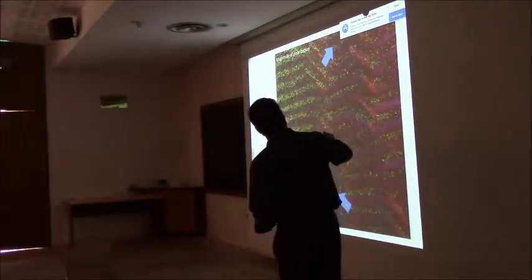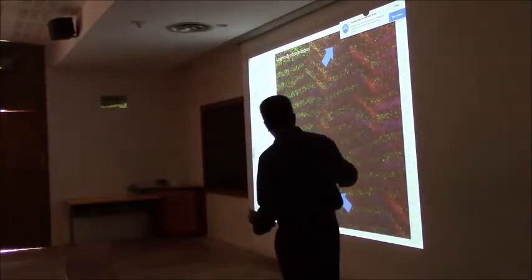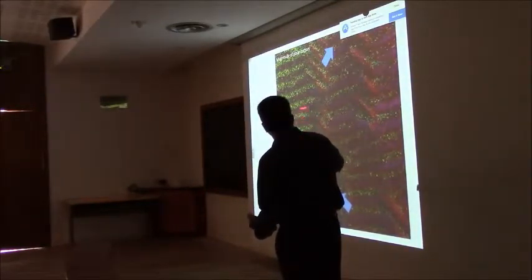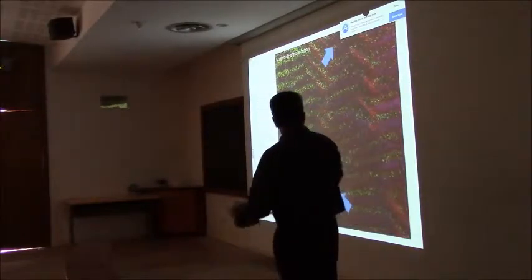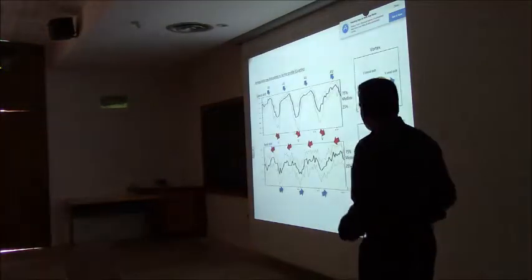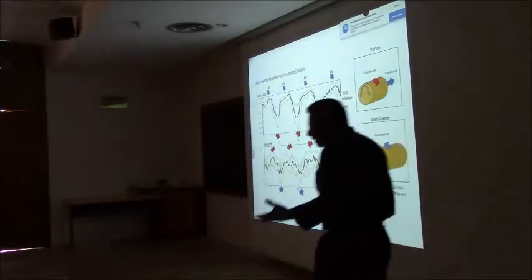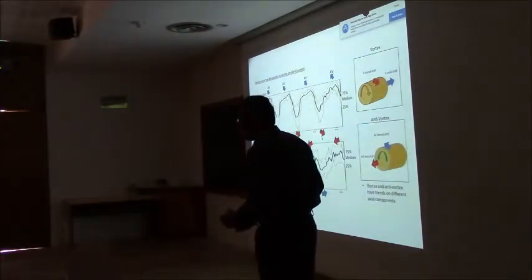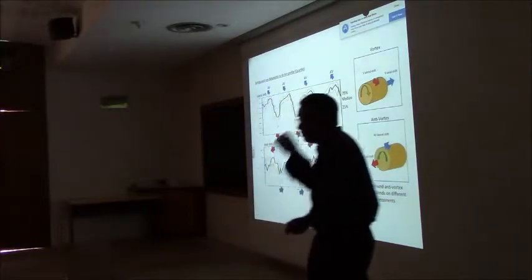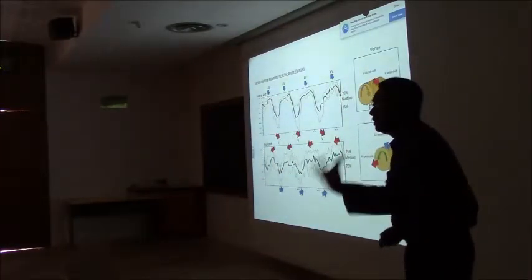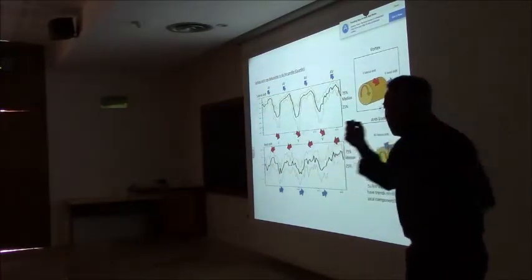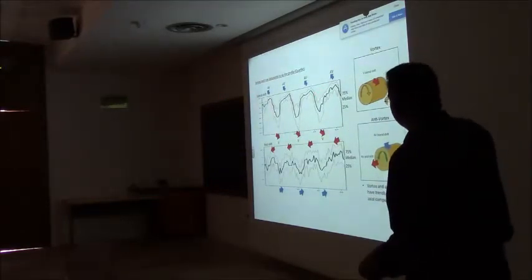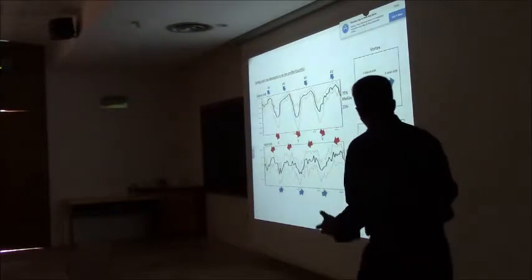This is basically looking at the top of the sample. These are the vortex, anti-vortex, you can see in green and in black. And so let's go a little bit deeper into it. What we've been doing is going to atomic resolution imaging again and looking at local displacements. These are very small displacements, you have to be incredibly careful. So I'm not showing you 90% of all of the background analysis, just to show you that indeed there's a lateral shift, which is pretty large. Anyway, it's not a big deal.